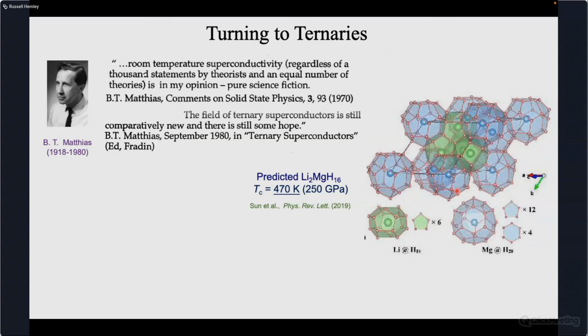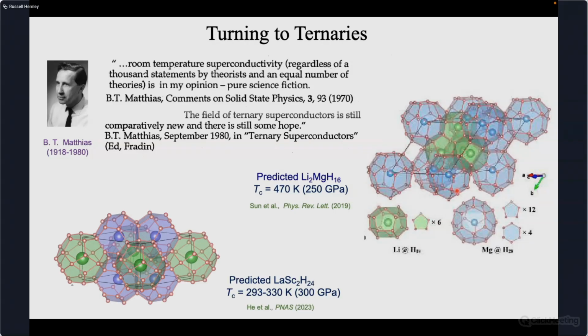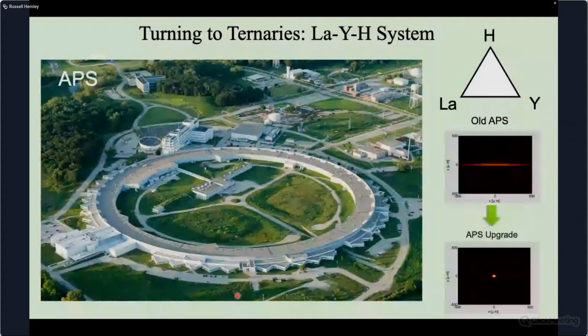In the approximations that were made in those calculations in the high temperature, the hot superconducting regime. I was also a part of some calculations that predicted if we replace some of the lanthanums with scandium in lanthanum hydride, you find other structures and interesting stoichiometries, including this one with a TC around room temperature and a little bit above, around 300 GPa.